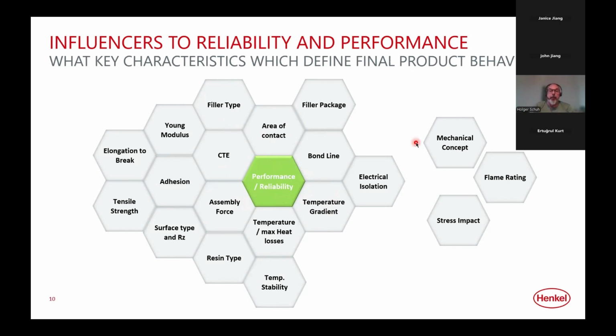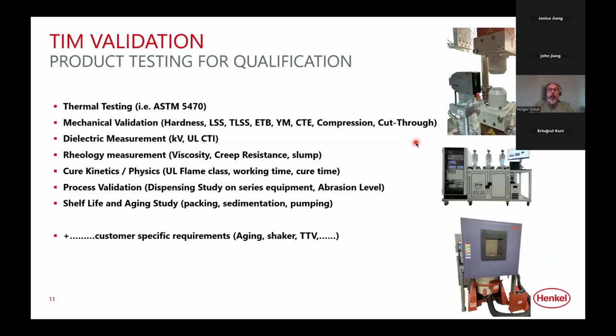When we do the materials validation, I mentioned it already in the beginning, we have all kinds of testing equipment available in our design and product development hubs across the globe. So our key competence centers are in the US, in Düsseldorf, in Germany, as well as in Shanghai in China. And here we do the thermal testing on the product according to certain standards. We do, of course, all the mechanical validations by ourselves. So checking, for example, hardness, lap shear strength, tensile lap shear strength, elongation to break, and all those kinds of characteristics of the material. We do all kinds of dielectric measurements. We also have a Henkel UL certified lab where we could do all kinds of lifetime testing, CTI testing for high voltage application. We do the rheology measurements, so viscosity, creep resistance, and slump technology. We check, of course, the cure kinetics on the material.